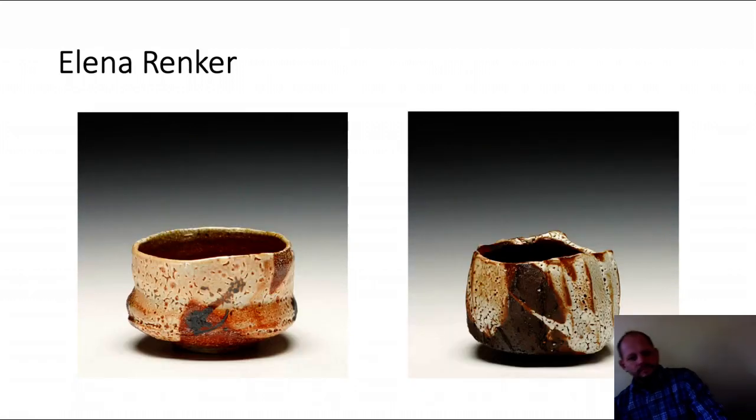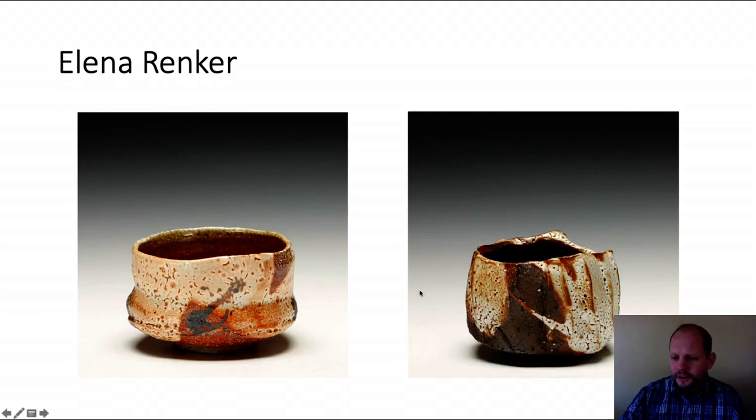These are examples of Shinos, which is a feldspathic glaze, typically a lot of sodium feldspar, a lot of clay. And you can see how the hues of iron are coming through from the clay body and the trace sources of iron presented in the glaze from the clay addition.